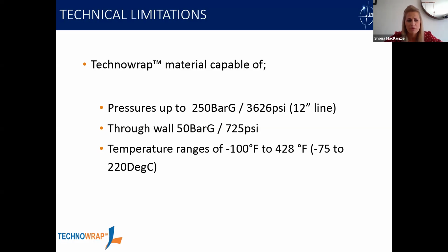So of course there are limitations with composite repairs. In terms of the pressure limitations, you're looking at around about 3,626 psi. That's on a 12-inch line. Of course, that will vary slightly dependent on the diameter itself. So the smaller the diameter, the higher the pressure it can see, but that's just as a general rule of thumb. If the defect itself is through wall, we are limited to a pressure of around about 725 psi. And that's for a leaking defect. Temperature ranges. So this is an in-service temperature of -100 Fahrenheit to 428 Fahrenheit, or -75 to 220 degrees Celsius. So there's a good range of temperatures covered for in-service temperatures there.